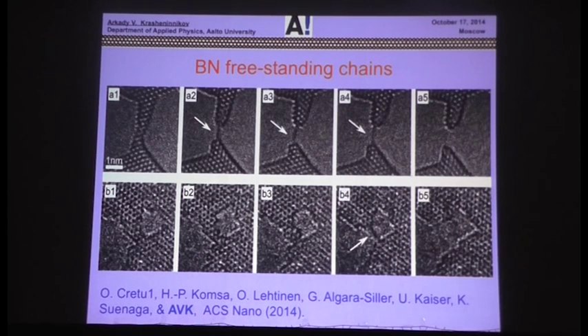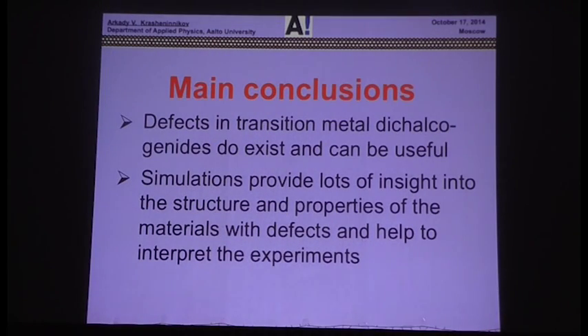And what's interesting about one-dimensional chains of ionic materials is that metal chains have been observed, or carbon chains have been observed many times before, but these are the first two observations of chains in ionic materials, because ionic materials should be much less stable as the coordination number drops, I mean the number of neighbors for a given atom. But still they can exist even though under quite special conditions. So essentially that's all I wanted to tell you today.